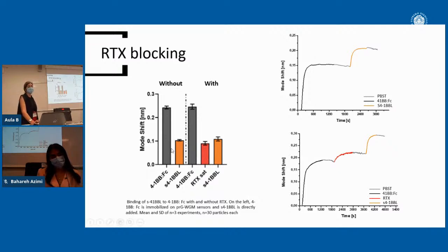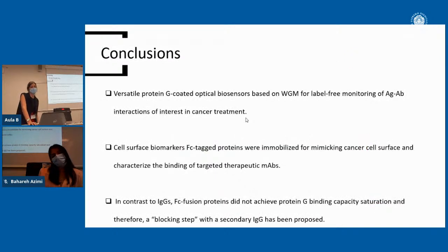So not two different binding pairs, but one binding pair in which the ligand does not have an Fc fragment. We immobilized one cell surface biomarker, in black, and then in one case we added rituximab, and in the other case we didn't. Then we flowed the analyte, which is a soluble ligand without any Fc fragment, and we compared the binding of the ligand in the two situations. We observed the same amount of signal and the same behavior in the curve. So with this, we can conclude that, at least in the experiments that we performed, rituximab was not altering the interaction.